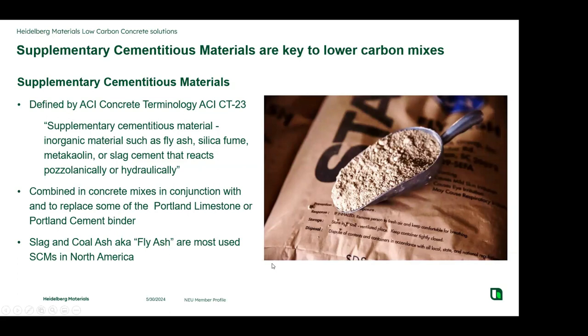To get there and to make these mixes low carbon, we're going to utilize supplementary cementitious materials to a great degree. As ACI defines these materials, they're essentially something that reacts pozzolanically or hydraulically within the mix. They will almost always react with calcium hydroxide, which is a hydration product from within the Portland cement system. They'll be combined in there, and we will reduce our Portland limestone cement or our Portland cement binders by replacing them with these supplementary cementitious materials. Most of the time here in the United States or in North America as a whole, these supplementary cementitious materials would be fly ash or slag.